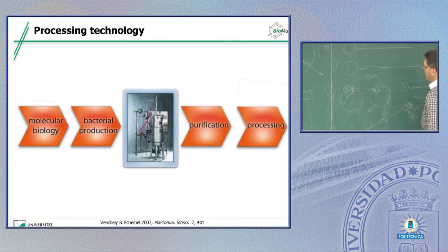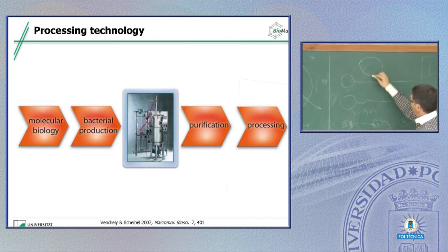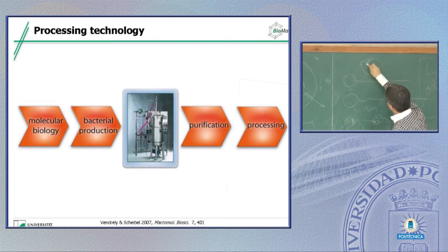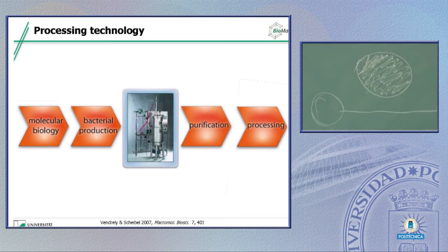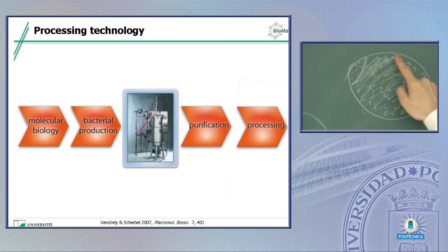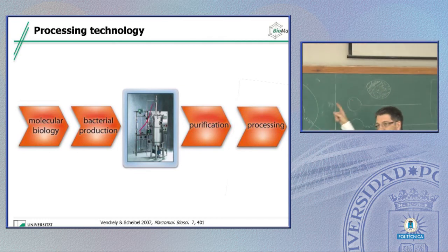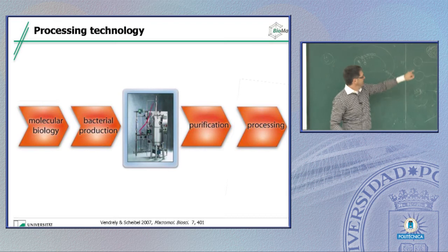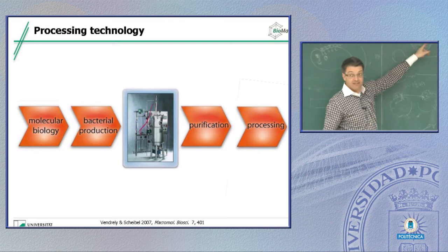If you check such a bacterium in the electron microscope, this is the bacterium, and it pretty much looks in the electron microscope like that. So you have high electron density in that part, and then you have typical transparency up here. And this high electron density, that's silk protein. So 85 to 90% of the bacterial cells are packed with silk protein. And this tiny little bit is the rest of the bacterium that it needs for survival. This is still soluble.